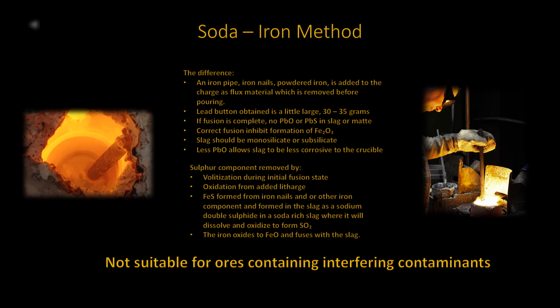During the start of the fusion, the sulfur starts to volatilize. As things heat up, the oxygen from the oxidizing compounds, mainly litharge, combines with the sulfur, producing sulfur dioxide gas. The sulfur will also combine with the iron, forming iron sulfide, which further combines with the soda to form a ferrous sodium double sulfide. The desulfurization is caused by the reaction with the iron rod, nails, powder, or other form of added iron. The iron nails, rods, and or pipes are removed just before the pouring into the cone molds. Depending on the ore type, the accuracy of this method may be scarcely less than the litharge niter process.